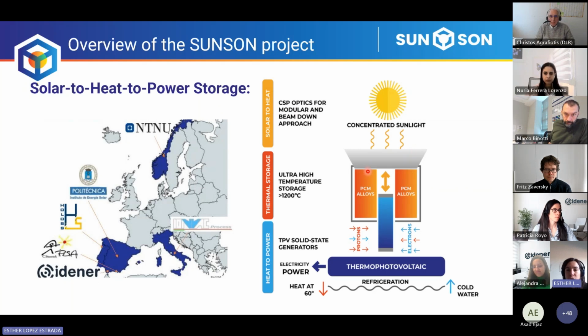And then this energy can be used to heat up a phase change material. So this energy can be stored as latent heat. And the idea is that if the PCM achieves very high temperatures, which means above 1000 degrees Celsius, then this PCM becomes incandescent and it can be used to illuminate photovoltaic cells. And these devices can convert this radiated heat into electricity just by using low bandgap semiconductors that are suitable for the spectrum illumination of incandescent bodies, which is why these photovoltaic cells are called thermophotovoltaics.